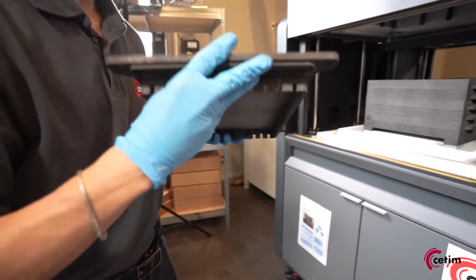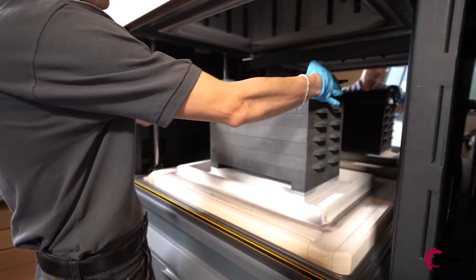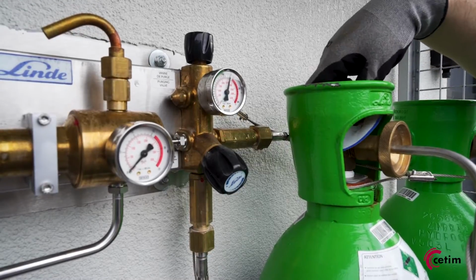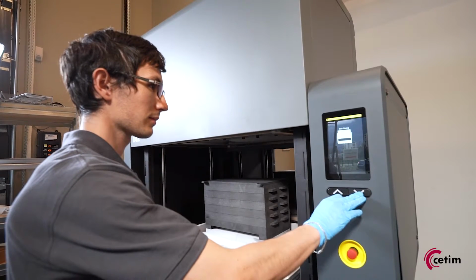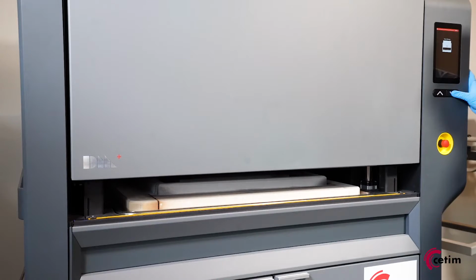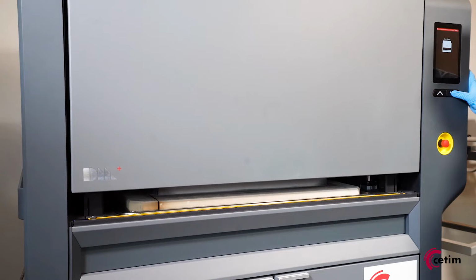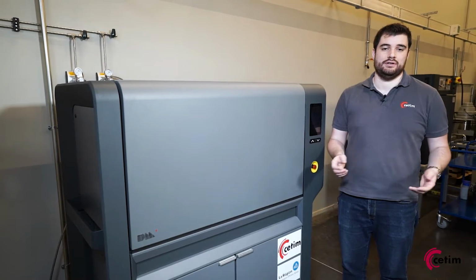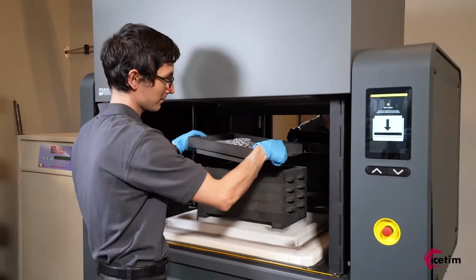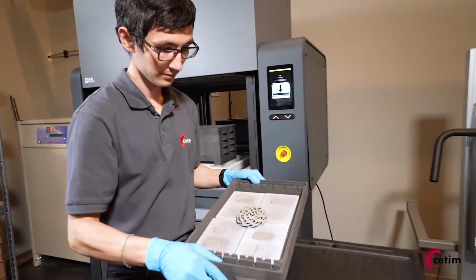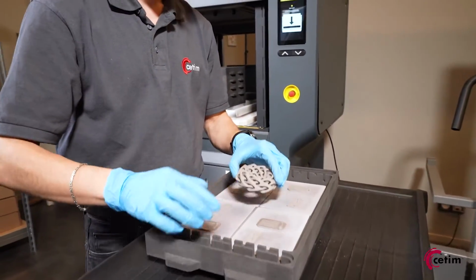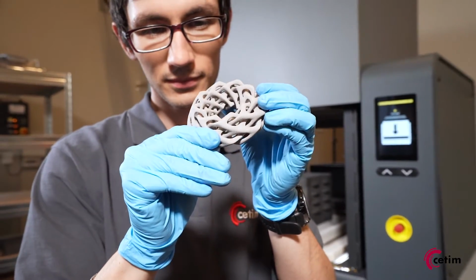A vacuum pump will remove the oxygen in the chamber before replacing it with sintering gas. The furnace will first reach the debinding temperature and then rise up again to its sintering temperature. The sintering usually lasts 1 or 2 days in total, including the cooling. Once the cycle is finished, the furnace is opened and the parts can be retrieved. The consolidation step is now complete.